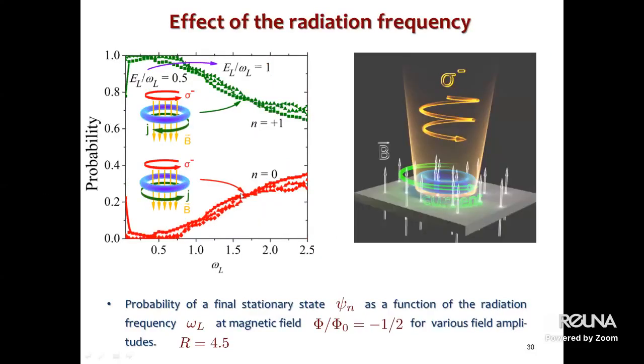Next result. Here, we investigate the dependence of the probability of realizing the final state on frequency. So probability is a function of frequency. For counterclockwise polarization, the imbalance between the probability for n equal to 0 mode and for n equal to 1 mode quickly reaches unity at small frequencies and remains relatively constant up to omega approximately 0.7 here. Afterwards, it starts to decrease monotonically at high frequencies. Here I show only one polarization, because for the other polarization it will simply be a switch between these two curves. Red will be here, green will stay here.